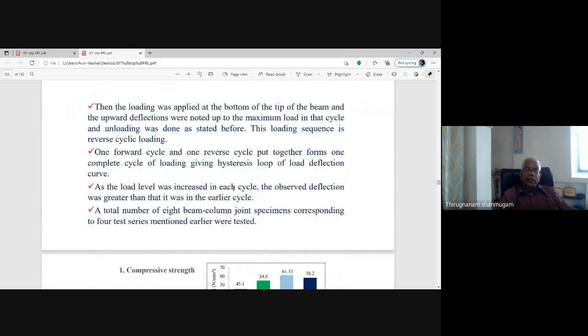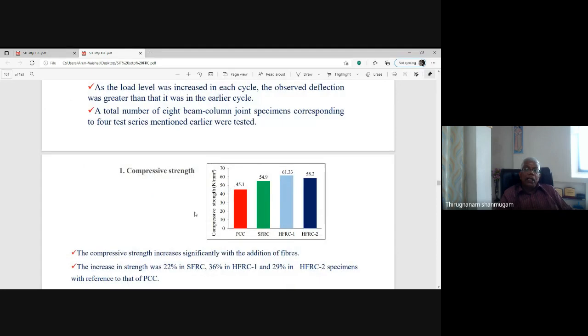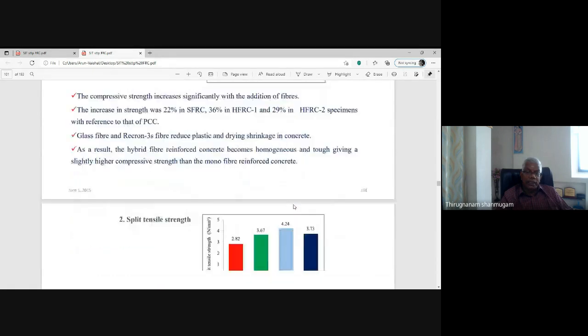The results are plotted like this. For conventional concrete, 45 Newton per mm square, even though it is designed for M30 grade, we are obtaining, because of the high quality control, 45 Newton per mm square as the compressive strength for the conventional concrete, and 55 Newton per mm square for fiber reinforced concrete, 61 or 58 Newton per mm square for the hybrid fiber reinforced concrete.